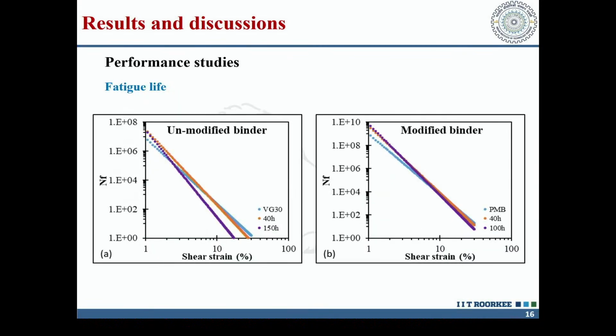Then we have seen the fatigue life. Fatigue life is again more, if you see here, that it is going up to 10 to the power 10 for modified, while for unmodified it is going as 10 to the power 8 in this case. And at the lower shear strain, you will find the life is more. As the shear strain is increasing, the life is also coming down.